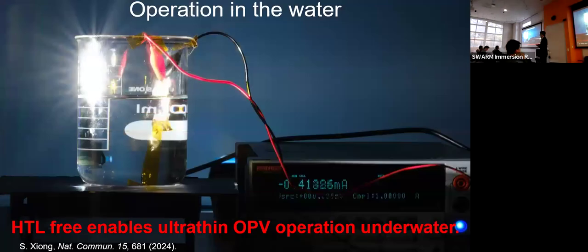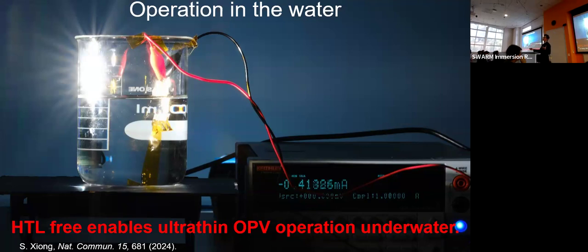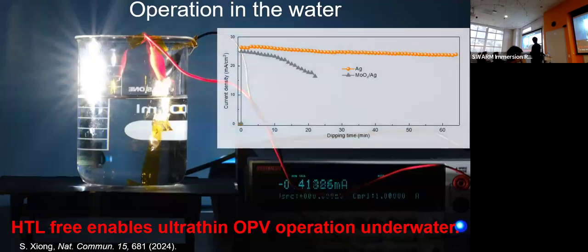Okay. Then the new HTL is very beneficial to improve the water stability, because normally we are using water-sensitive HTLs such as PEDOT:PSS or molybdenum oxide. Both are very water sensitive. Silver oxide is not sensitive to water. So this is proof of the water stability in comparison with the existing normal HTL systems. The orange curve shows our newly developed system.